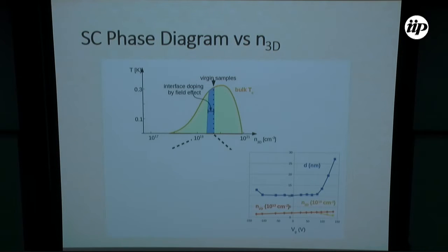Now if you look more in detail, the 2D carrier density, that is the red lines, is continuously increasing as a function of gate voltage, like in a capacitor. So from that value, now we know the thickness for all the gate voltages, so we can calculate the 3D carrier density. And what we see is that it keeps increasing as the thickness is constant, but when the thickness increases and doubles in the overdoped regime, the three-dimensional carrier density actually decreases.